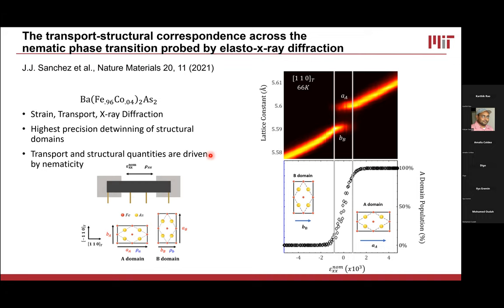The claim to fame of this paper is that it's the highest precision measurement that's been done of detwinning the structural domains. So I'm using tunable strain in order to change the domain states, and then I'm using X-ray diffraction to monitor how the lattice constants and how the domains are changing. So let's walk through this figure here. This is a diagram of a single crystal sample mounted on two titanium plates. By applying voltage to the piezos, I can move these plates and apply strain to the sample. My sample is oriented so that within the nematic phase, I have this A domain and this B domain, where the longer lattice constant of the A domain is aligned with the stress axis, and the shorter lattice constant for the B domain is also aligned to the stress axis.